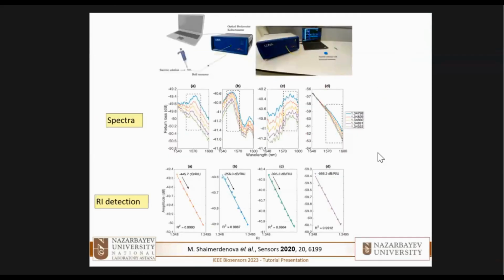This is actually how we interrogate the device. So we take an analyzer, this one, that is used already in distributed sensing, and we monitor the spectrum at the tip of the fiber. So we set the distance at the tip of the fiber, and we monitor the spectrum right there. And these are some of the spectra and the way they change with different refractive index values.